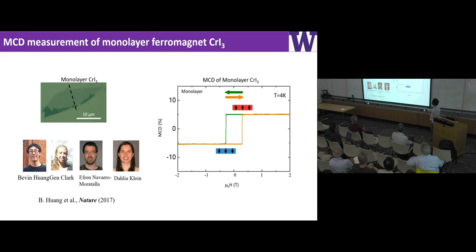This is what we measured many years ago on a monolayer ferromagnet in collaboration with Pablo's group. What I show you is the MCD signal as a function of magnetic field, sweeping up and sweeping down. So there are key features, right? You see there's a finite MCD signal at zero magnetic field, and then also you see a hysteresis loop. All these are hallmarks of ferromagnetism in a monolayer.